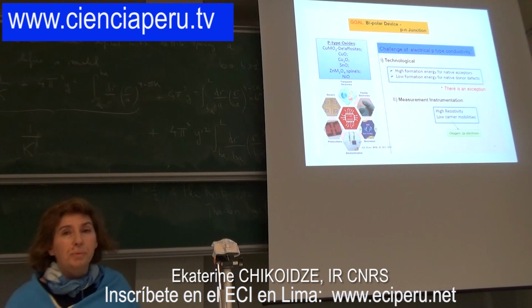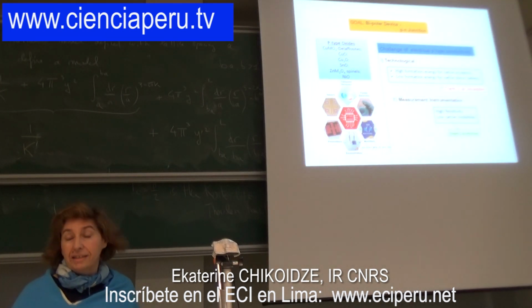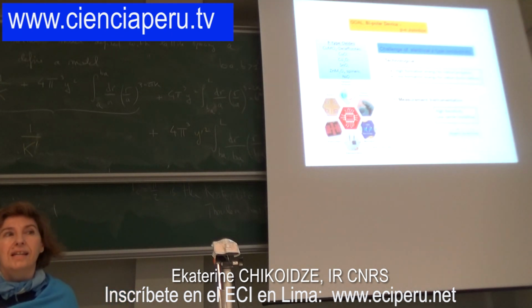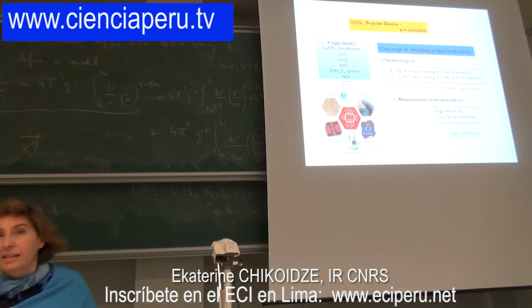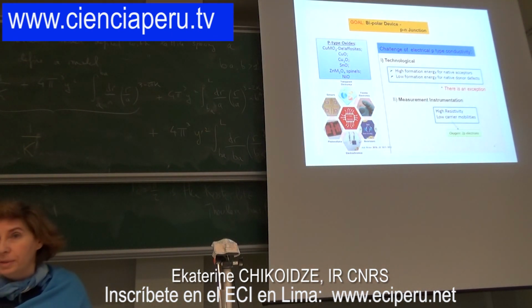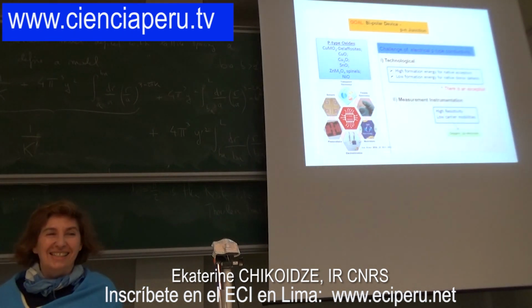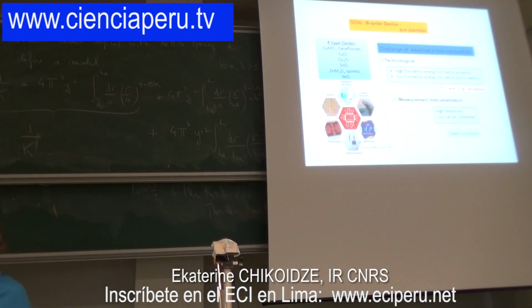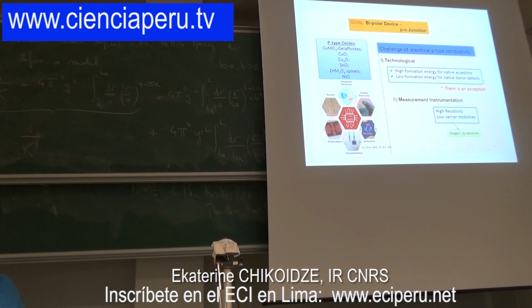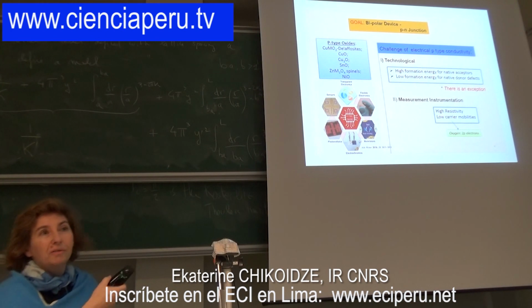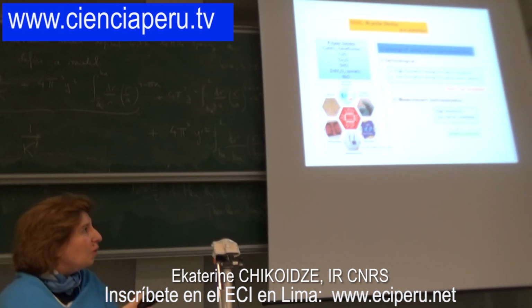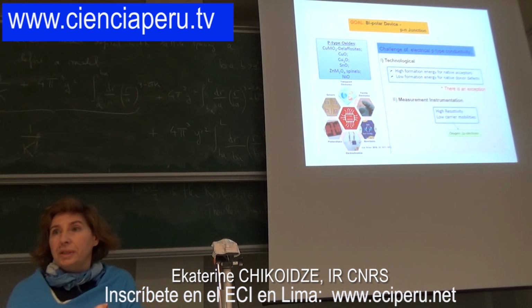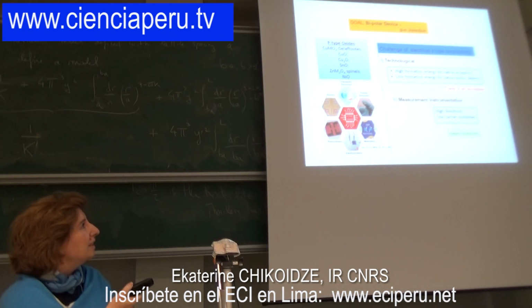So for oxides, the big problem is that there is an asymmetric tendency of doping. What does it mean? Oxides tend to be doped very easily to be N-type, but there is a problem of P-type doping in oxides. I think he skipped slides showing that zinc oxide has been challenged to be P-type for more than a century, and still it is a problem. It's a really general problem of oxides because of the nature of oxides: in the chemical formula we have oxygen, and this oxygen has 2p electrons, which makes doping problematic.